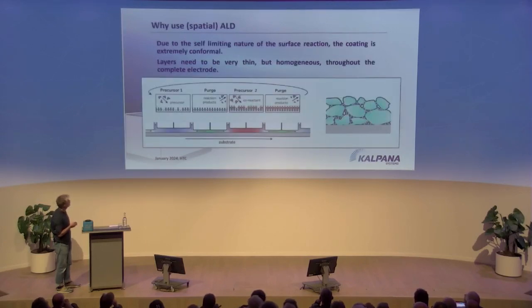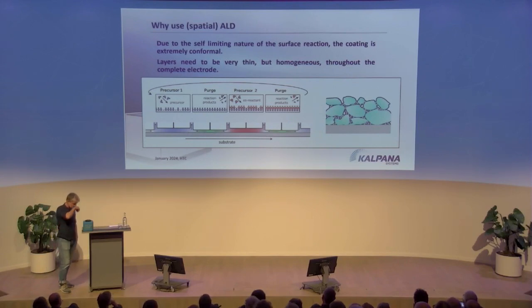Now, why should you use spatial ALD for that? Many of you probably know ALD, and it is a self-limiting reaction. The consequence of that is that the coating is extremely conformal. And this is what you need when you look at this picture, because it's important to make this layer thin, homogeneous, but also homogeneous all the way up, all the way down to the current collector.